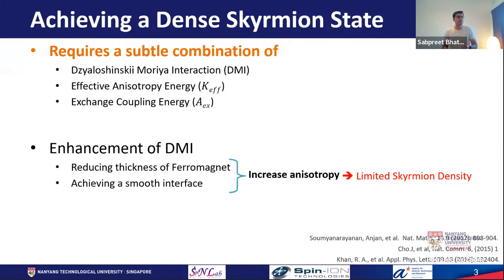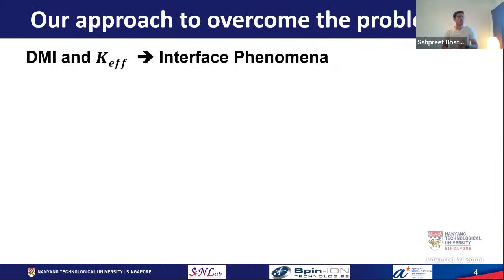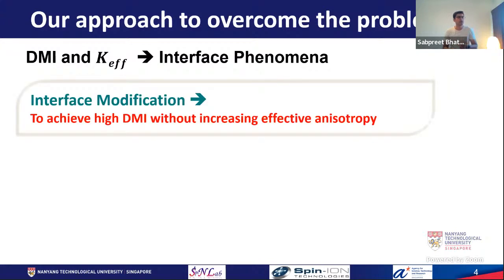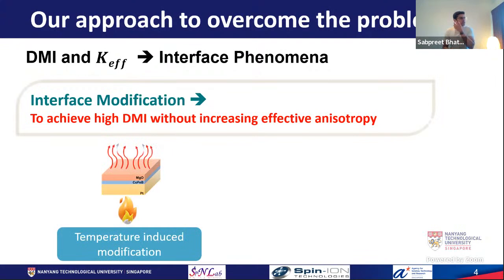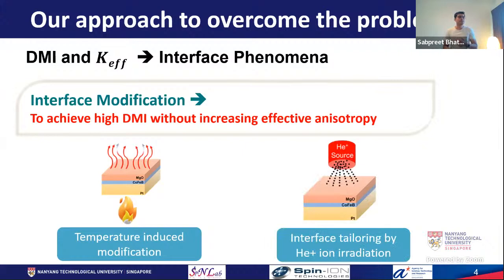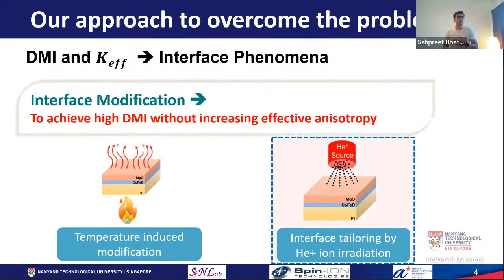In my talk, I would be talking about a way where we have achieved high DMI without increasing the effective anisotropy energy. Our method is based on manipulating the interface of the material, where the DMI and K effective are both interfacial phenomena, and hence we can manipulate these two properties. So here we have used two methods. First is temperature induced modification, where this modification induces the diffusion of atoms at the interface. Second is via helium ion irradiation, where it introduces the intermixing of atoms at the interface. And we were able to observe promising results using the helium ion irradiation.